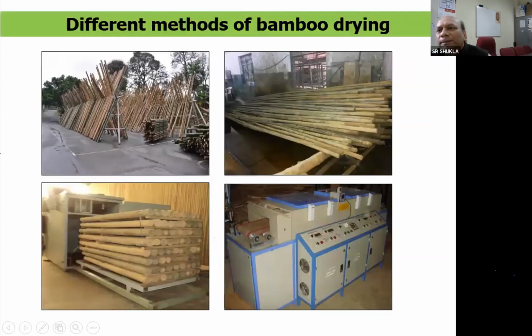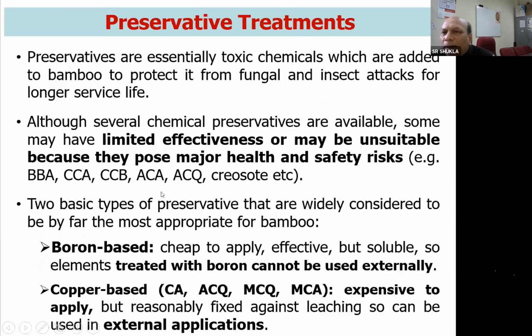When we use the bamboo, particularly for furniture applications, the bamboo should be dried and then used. So the thumb rule is that it is always better to work with dry bamboo, which possesses higher strength also. When moisture is removed and bamboo or wood in any way becomes drier, its strength also goes higher. Now these are the different ways by which bamboo can be seasoned, depending upon the amount of time and the investment we can make. So it is open drying, and this is drying in shade. We have kiln drying here, and this is the latest microwave drying, where a very short time is required, and bamboo can be dried in a quicker and better way.